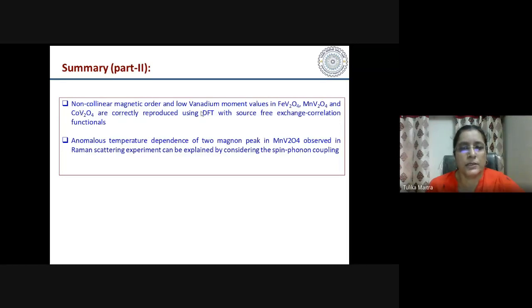So summarizing this part, non-collinear magnetic order and low vanadium moment values in these compounds FeV2O4, MnV2O4 and CoV2O4 are correctly reproduced using density functional theory with a suitable exchange correlation functional, and the anomalous temperature dependence of the 2 magnon peak in MnV2O4 observed in Raman scattering experiment was explained by considering the spin phonon coupling.